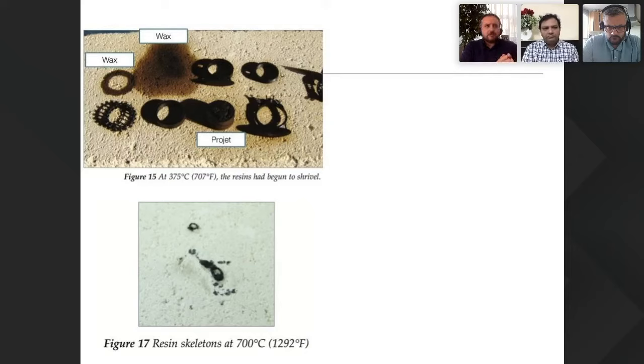So what happened here is when you compare casting between wax and resin, never think in terms of temperature and say, well, wax is melting at around 80 degrees, it's already melted. So if you have the tree of your investment, this is already melted. If you have your rings on your tree, these are already melted, then they're at the bottom, waiting, let's say. And when you increase to 200-300 degrees and even more, the wax is going to fly off, okay.